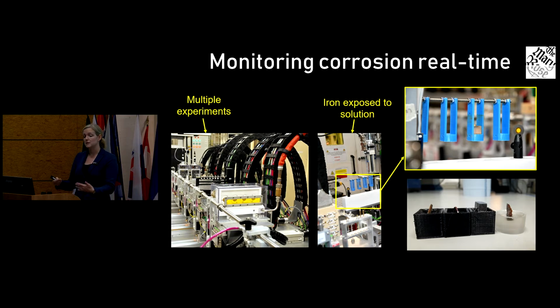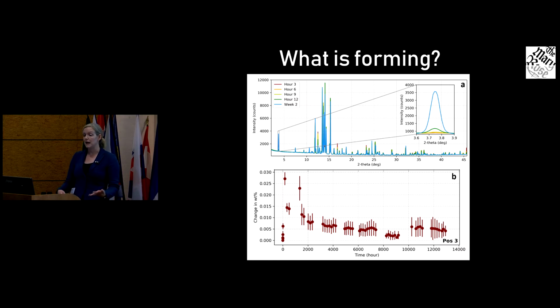We put it into a solution which is typically used as a passive solution for looking after these kind of materials. And then every week we've been collecting diffraction patterns. And all of this data is being looked at now, but just to give you an idea of the kind of thing we can get from this, this is the freshly excavated iron, and the peak that's highlighted there is this very damaging product, akaganeite. So you can see over the hours, as it's exposed to this solution, how that starts to form. We can then do refinements on this data and look at the weight percentage of the different phases there, and you can see over time that you've got quite a lot of akaganeite, and then that does tail off. It transforms into something else over time.